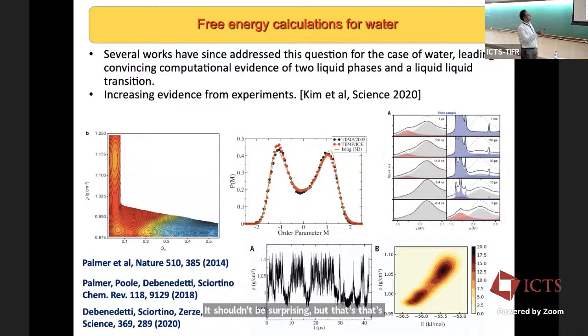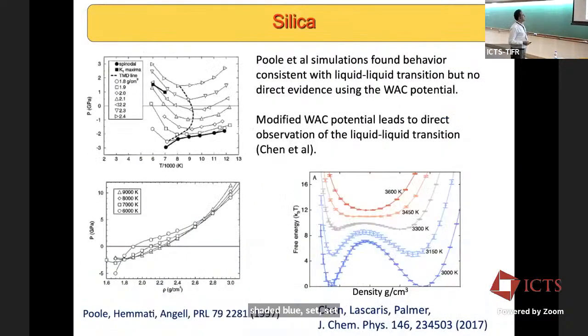And more interestingly, perhaps, there have been some very fast pump-probe kinds of experiments, which reveal that indeed there is a meaningful window of time, though all in nanoseconds, where one observes a transformation of this initial high density liquid phase to the low density liquid phase much before the crystallization that is shown in this shaded blue sets in. Okay, and this I'll skip over,